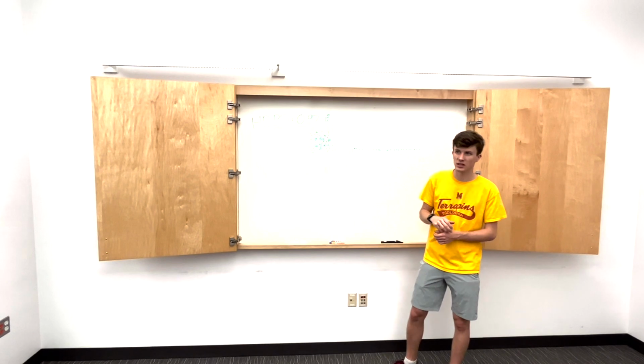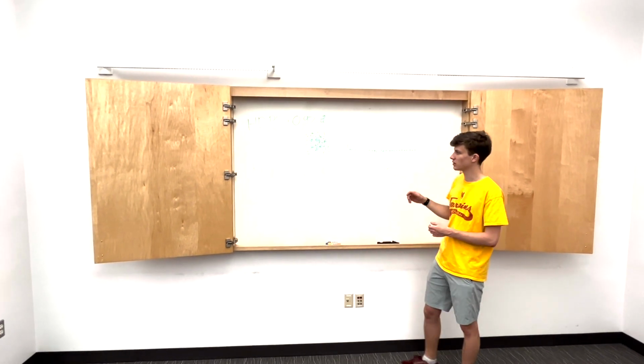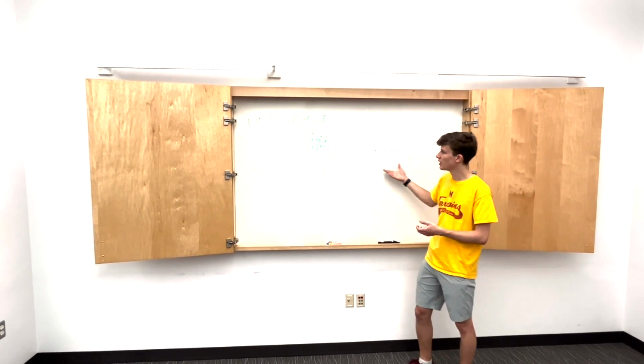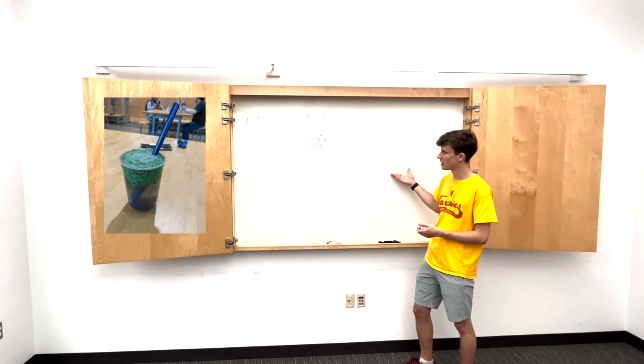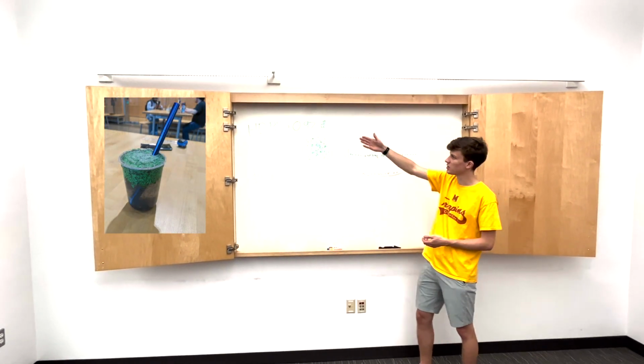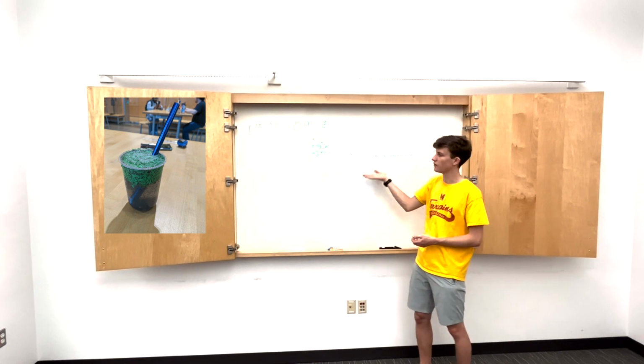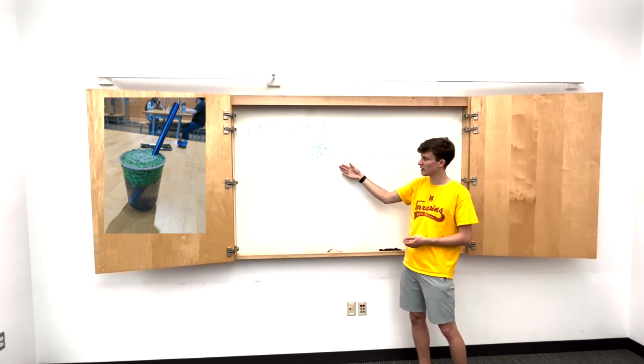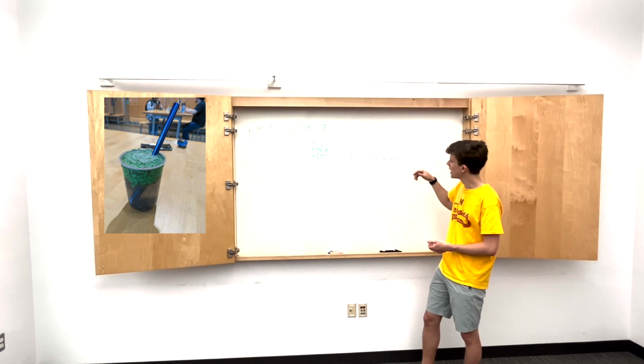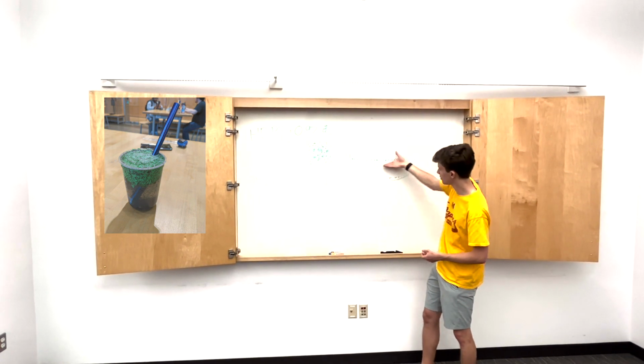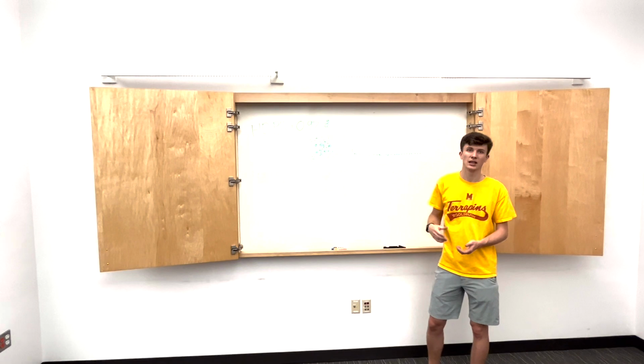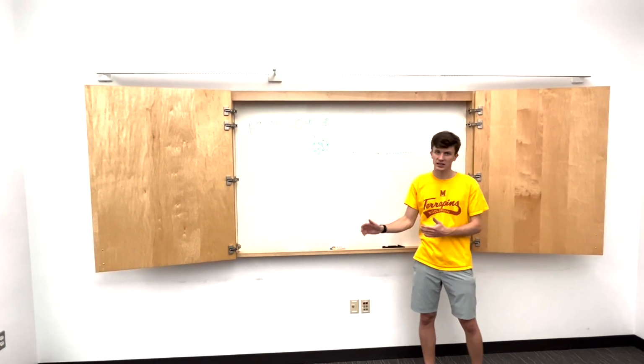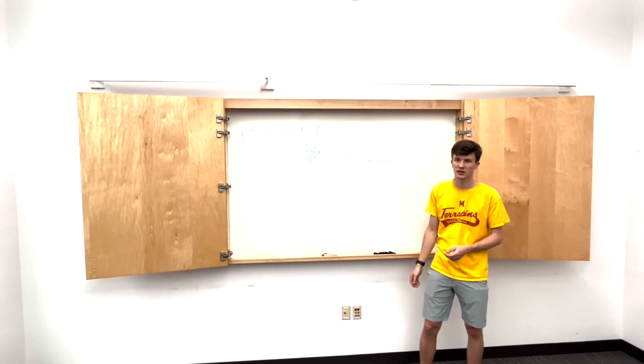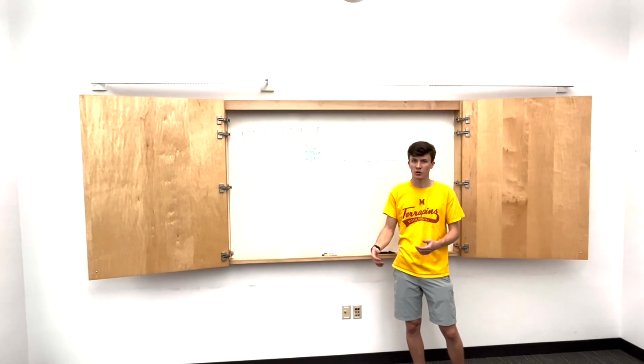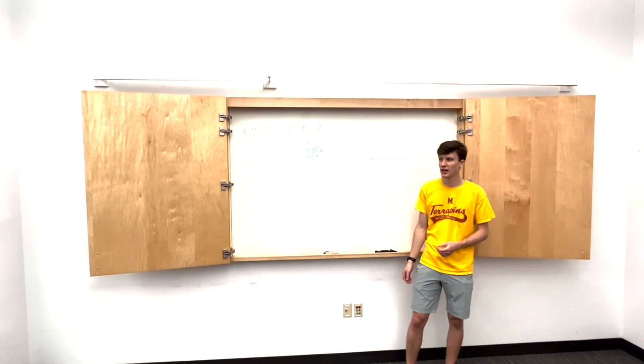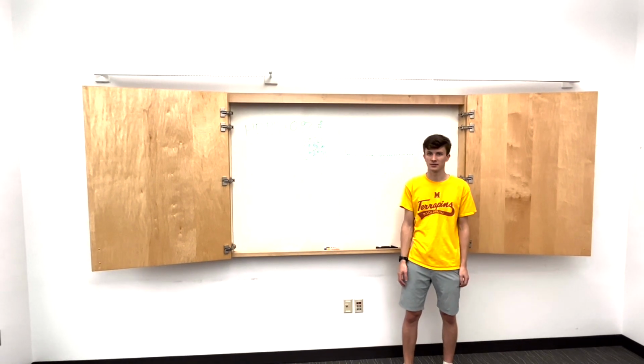And we did this using a gravimetric process, which pretty much included dumping the two materials into a container of water. Since HDPE has a density less than water, it floated to the top, and since PLA is more dense than water, it sank to the bottom. And then with a little bit of stirring, we were able to scoop out the HDPE from the top, giving us a clean, pure material. We still had some issues with small particles of PLA attaching to the surface of the HDPE, but we were able to consider that a non-factor, and that allowed us to continue forward.